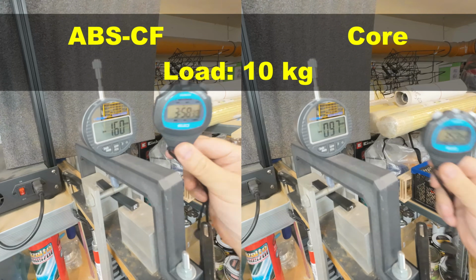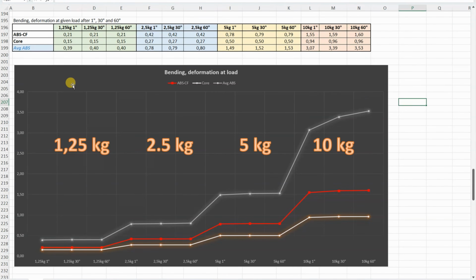Smaller values are better, less deformation, and we can see that the core is better compared to the ABS-CF, less deformation, but both are very good compared to the non-reinforced ABS. Additionally, under 10 kg you don't have that significant additional deformation during this 1 minute, unlike the average ABS.